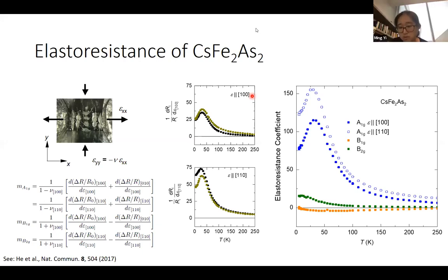I see. So the same story for cobalt, I guess? Yeah, for cobalt you can dope more, and then you finish around 12%. I see. The other question is in the other type, the underdoped potassium-doped barium 122, even in the C4 phase, there have been PDF measurements that show that locally the crystal is still orthorhombic. Correct. Do you know if it's the same story for this material, 144? I don't know about PDF measurements in this one. It's possible that I missed that. Well, since the nematic susceptibility seems to be finite, I don't see why it should not be locally distorted. Yes, then it's a matter of degree. Okay.